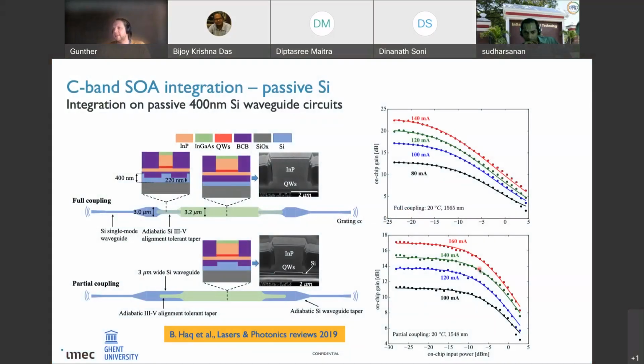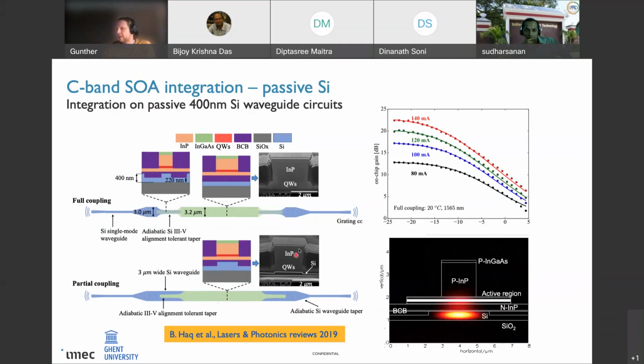So for indium phosphide on silicon devices, the first thing we did is demonstrate an SOA, where we transfer print an indium phosphide PIN waveguide structure on top of a silicon waveguide structure. In this experiment, we actually made two designs. One where the light is completely transferred from the silicon into the III-V, so the mode is completely confined in the III-V in the gain section. Or a second structure where, as shown here, the mode is only partially transferred from the silicon to the III-V.